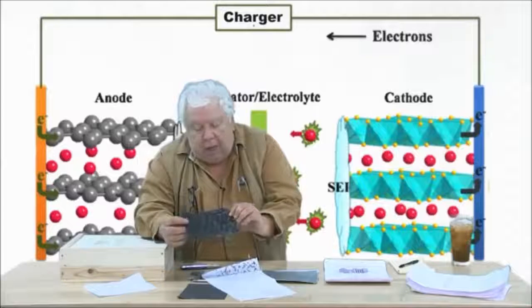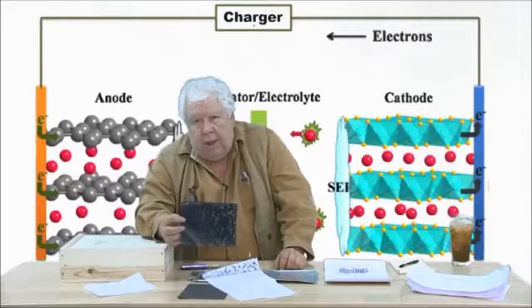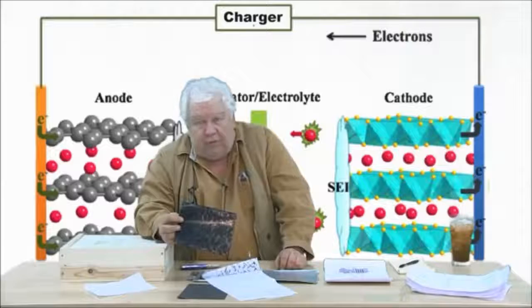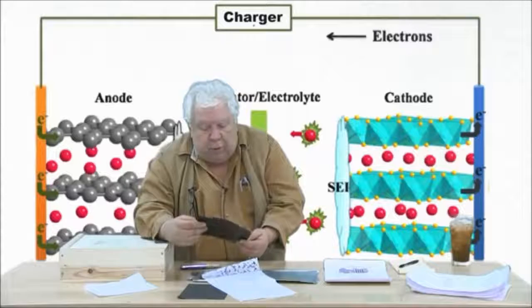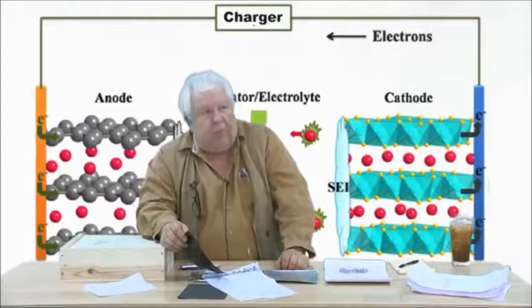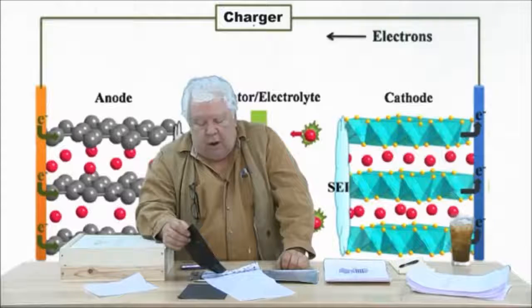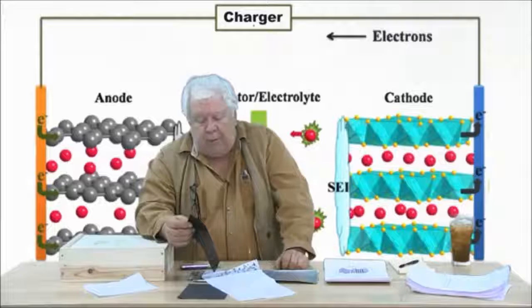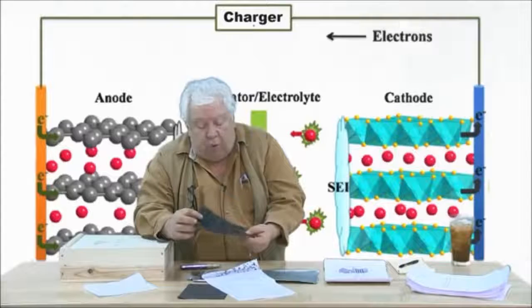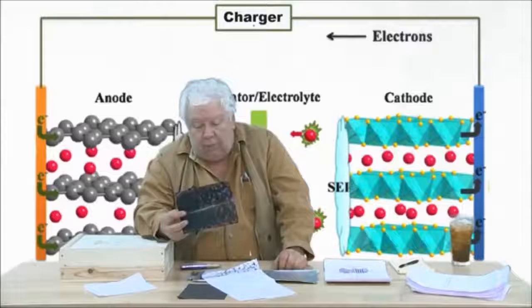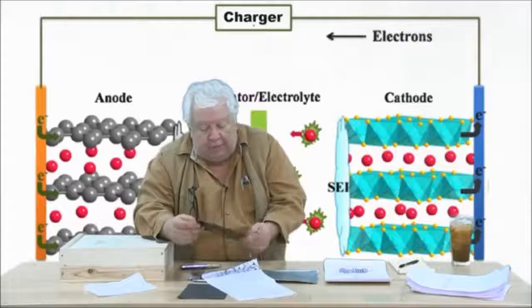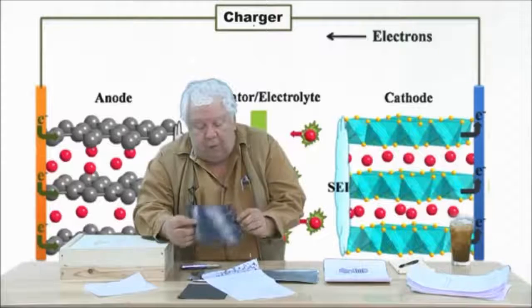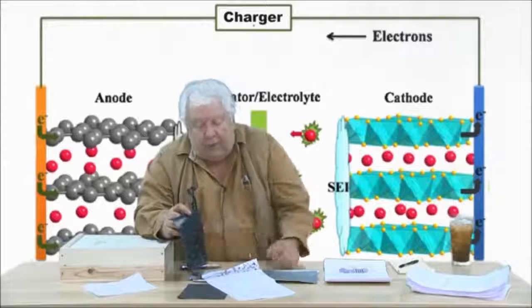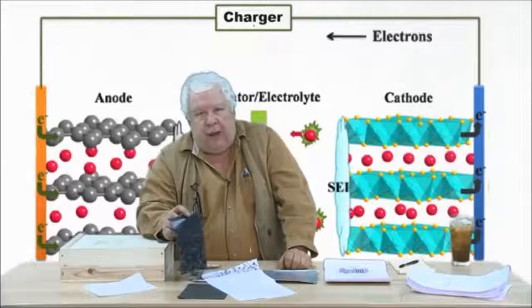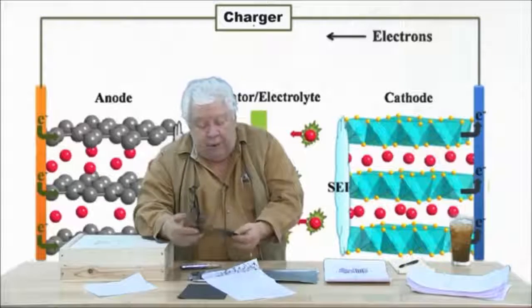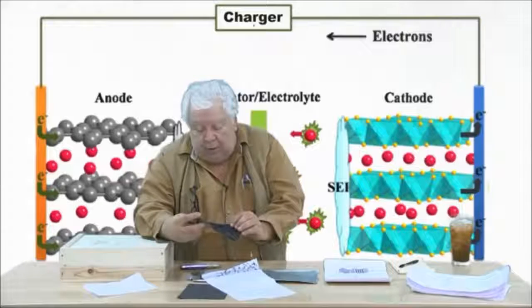Now this side has a lot of copper on it. And that's a sign of an over-discharged cell. And we'll talk more about that later. But when we over-discharge the cell below a certain potential, the copper that the anode's on begins to come apart. And it migrates throughout the battery and can form shunts and dendrites to short the cell, but it also deposits elsewhere. Here in this case, you can see it deposited on the cathode. Every place this copper is deposited now no longer can intercalate lithium ions. The copper blocks that. And we've got quite a bit on one side, a little bit on the other.